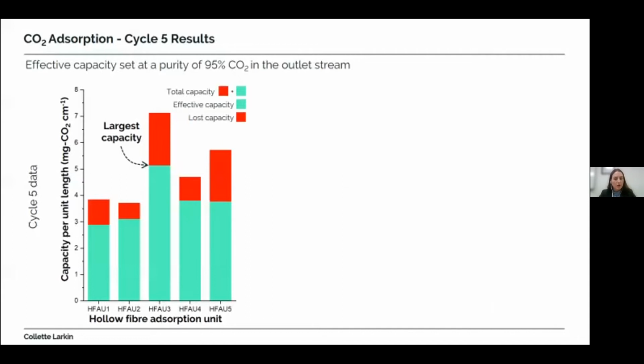But another important criteria is the purity of the CO2 capture outlet stream. In order to store the CO2 permanently, the CO2 captured should have a high purity. However, achieving high purities typically requires a lot of energy and it's costly. Studies conducted by Pera et al. discovered that at a purity of 95% CO2, liquefaction costs were reduced. Hence, I've defined an effective capacity as the capacity of the system to achieve an outlet purity of CO2. Although it should be noted that this does result in a portion of the total capacity being lost, which is what you can see there in red.